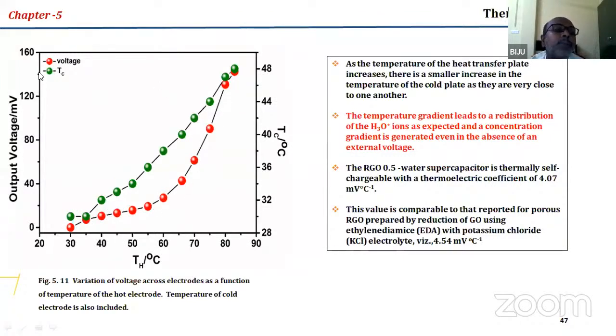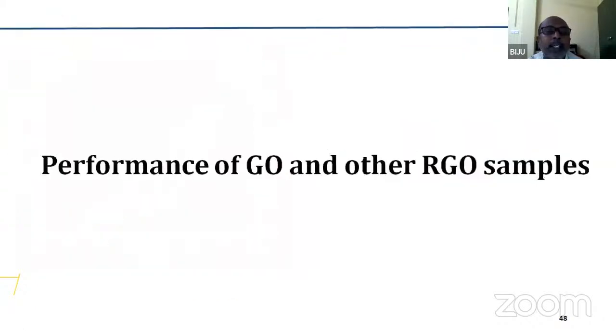It was actually up to something like 150 millivolt for this change. So the voltage generated is 4.07 millivolt per degree Celsius, which was rather good when you compare with the other thermally self-charging supercapacitors reported in the literature.